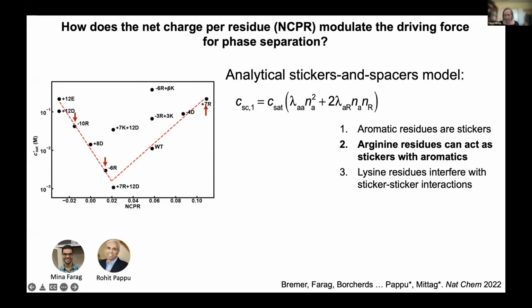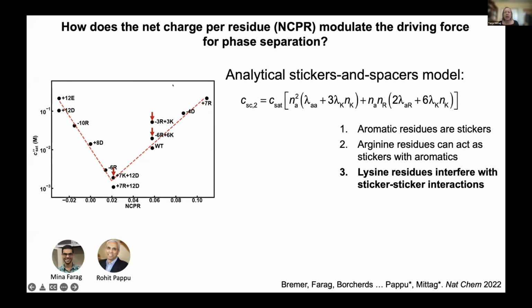And then the lysine variants were still outliers. And these data points really suggested that lysines interfered with phase separation. And so adding to our model 3-body interactions where lysine residues really interfered with aromatic and aromatic-arginine interactions now nicely moved over all our data points onto this V-shaped plot.